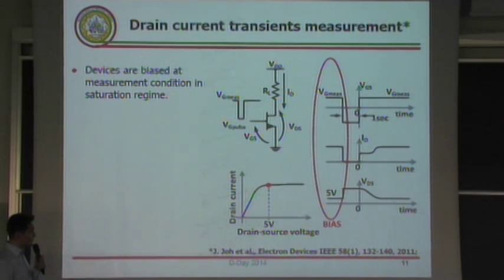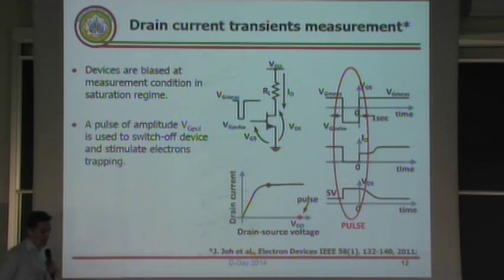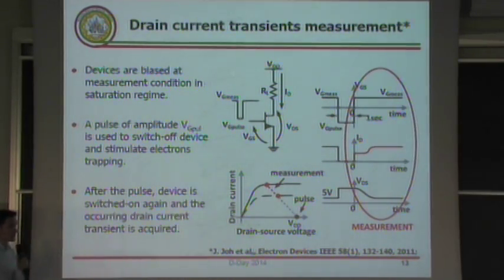The first step was to bias the device in the saturation regime with a constant VDS voltage, and then a negative gate pulse was applied to switch off the device. In this condition, the device was off with a high VDS voltage, so during this pulse, trapping was occurring. Then we switched on the device again to see how the device characteristics recover after the trapping. To see this recovery, we monitored the transient occurring on the drain current.